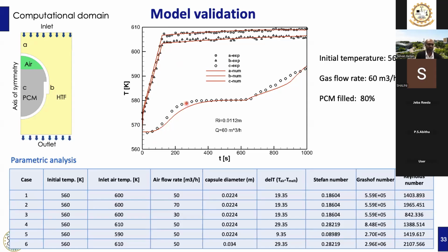And this profile shows the temperature of the capsule at the center. So numerically predicted and experimentally measured temperatures at different locations have been compared in this figure. As you can see, a reasonable agreement has been found.